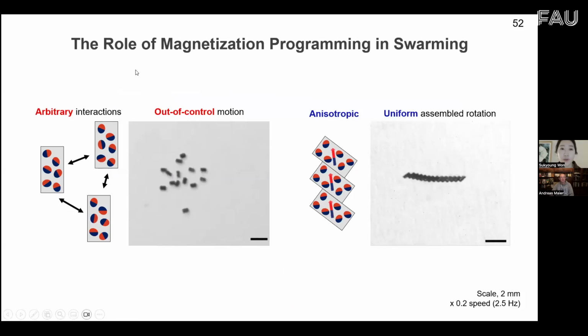And also, the magnetization profile control is important for the uniform swarming behavior, because when we did not apply uniform magnetization, the robots show random interactive communication with each other, resulting in out-of-control swarming behavior. However, when we apply uniform magnetization profiles in the microrobots, they are capable of uniform assembled rotation when we apply the rotating magnetic field. So we need uniformly magnetized microrobots.